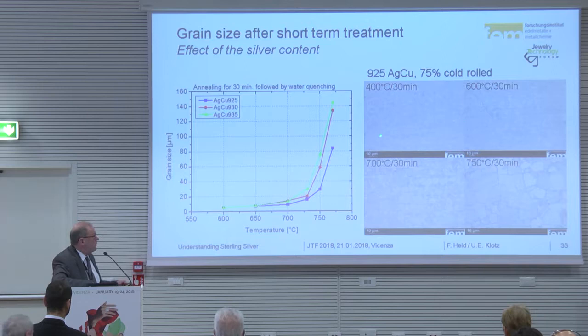This is a microstructure we see here, very small grain sizes. We use also small grain sizes, a little bit of grain size growing, but here we see the copper phase, and this is a grain size limiter. In gold, we will use iridium to get small grain sizes. If we get higher to 750 degrees, grain size really starts to grow because we are missing these copper phase lines.